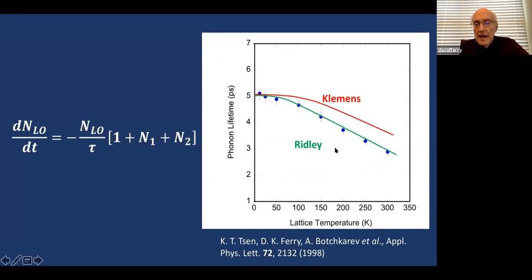The blue points are data points versus lattice temperature. So you can see this. And the green curve is the Ridley decay, and the red curve is Klemens, which doesn't fit the data. Now, we didn't expect Klemens to be very important, but Ridley certainly seems to still be very, very active.